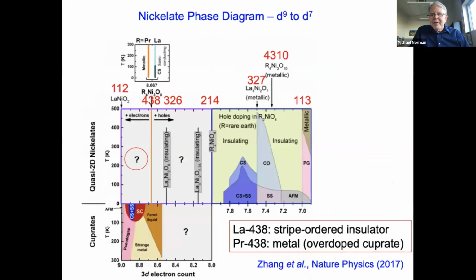But since then, we know a lot more about the phase diagram. Now people have been able to map all the way out from the d9 configuration, where nickel is 1+, all the way out to the perovskite d7, where nickel is 3+. Of particular interest are the line phases. You have the n=1 Ruddlesden-Popper phase, which is 214. You go to bilayer 327, trilayer 4310, all the way out to the perovskite, which can be considered as infinite layer. Then you can do what's called topotactic reduction, and you can get the 113 to reduce to 112, 4310 reduced to 438, and the 327 to reduce to 326. This effectively allows you to look at the electron-doped side relative to the 214 phase.